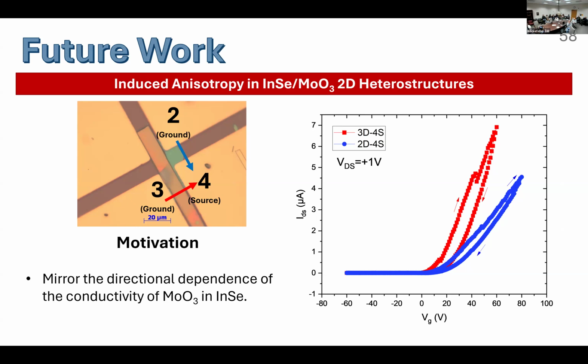And so here we can see that we've taken the transfer curves of an indium selenide device capped with an MoO3 layer, and we've looked at the transfer curves going in one direction as opposed to the other. We see that there is a distinction in the threshold voltage of one of these sides, not the other. Also, the maximum on current. So this is the potential avenue that I'm looking to explore.